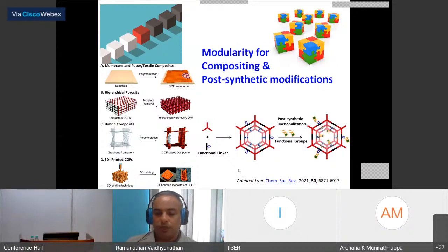And one of the key things we also would like to point out is the fact that you can do a two-step control on a COF's property by using this modular nature. So what you do, you use one of the modules to be a functional linker that will not interfere with the COF formation, but stays on the walls of the COF once the COF is formed. Now you can have a linker which is very connected to the functional group that is introduced in the COF already, and that can be made to covalently link with it. Thereby, you can introduce a very new functionality into the COF in a post-synthetic manner. And please keep this in mind, because I'll show you how this can be exploited in a real chemistry.